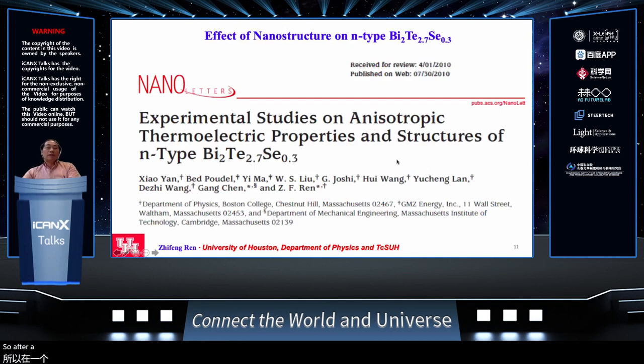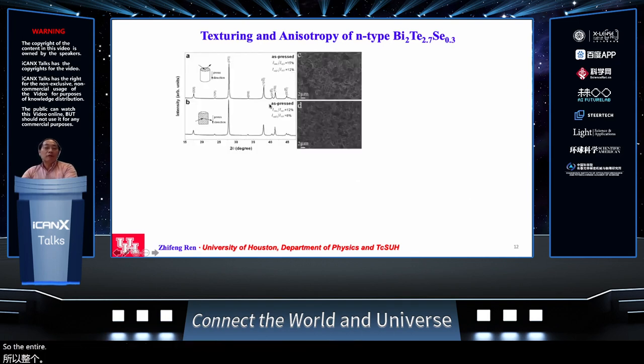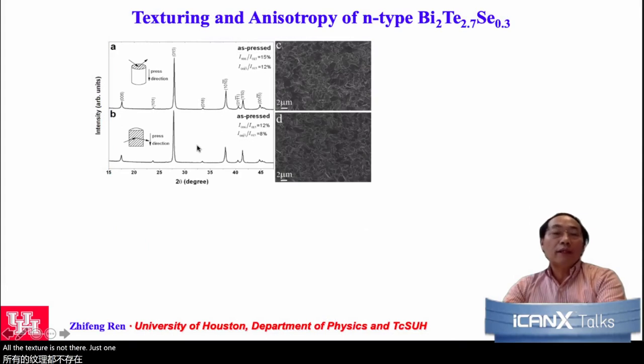So after this, we were thinking, when you have the P-type, you definitely would also like to improve the N-type. And we tried to improve the N-type. But N-type is a little bit different from the P-type. The reason is because N-type is very much anisotropic, not like the P-type. And so for the N-type, if you do the regular hot press, it doesn't matter whether it is in the press direction or perpendicular to the press direction, the texturing is not there, just one press. But then the property is not that good.